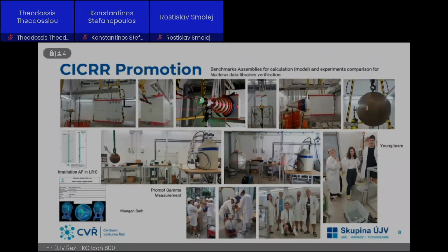This is the last measurement we finished about 2 weeks ago. This is a Teflon or PTFE. Again, there is a reaction at the floor. Maybe somebody can ask why we use this interesting cone here. This is because all these neutrons react also with the air, scattered from the walls and from the floors. So we have to measure 2 times. One measurement is performed without the cone, and you get everything. Then you measure with the cone, and if you subtract these 2 values, you will get a pure effect.